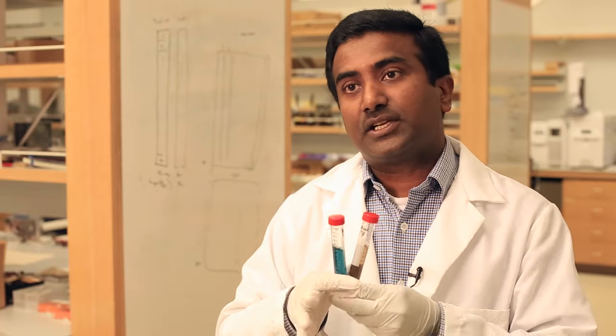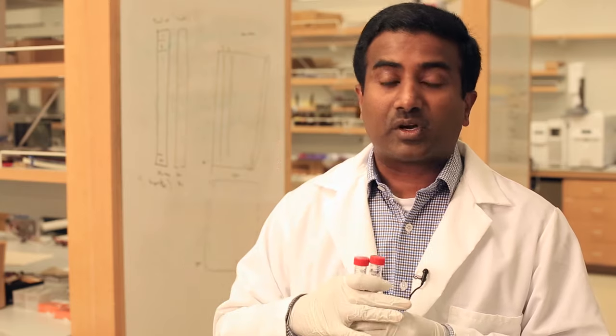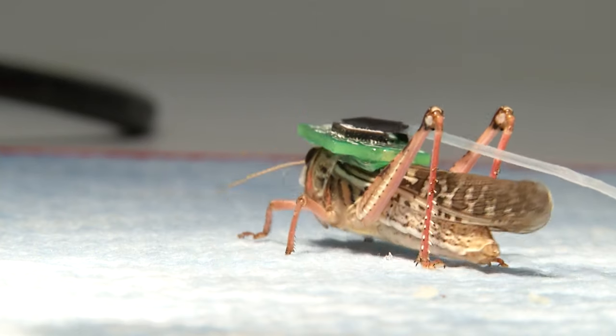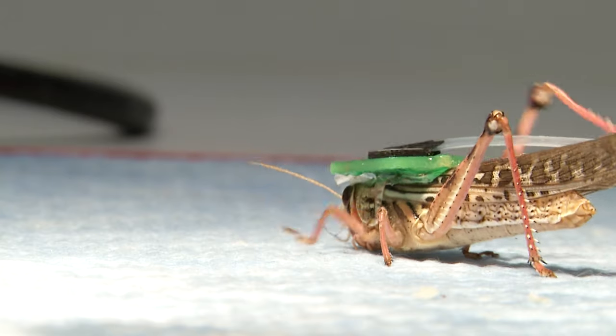The analysis is going to happen right on the wing because we have these nanostructures. These are actually gold nanoparticles that not only collect the sample but also dramatically enhance the chemical signals coming from the molecules adsorbed on this plasmonic patch.